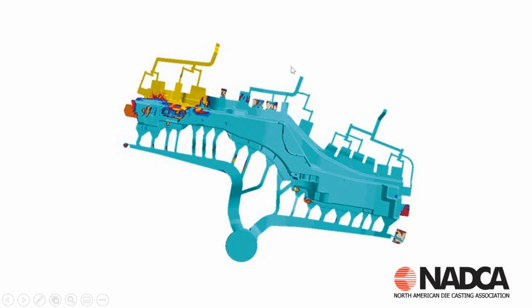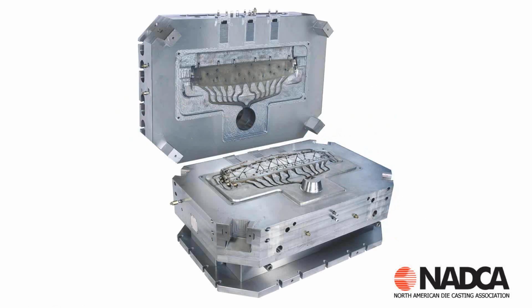And then we create a vacuum in multiple points, and we measure that vacuum in the casting. We want to be between 20 and 100, 150 millibars, definitely under 500 millibars. Otherwise, we're going to have trapped gases inside the casting. So we have the die cast die, we're gating this short distance, and we can see that. And then once again, we have multiple vacuums and a seal around the perimeter.